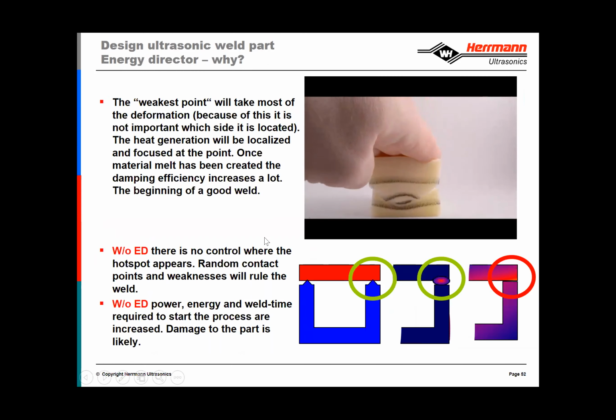And so furthermore, an energy director is absolutely required. If we had a situation like over here on the right, where the energy director is missing or lacking, the entire surface of the part typically is where the heat affected zone goes to, and that's undesirable. We want to focus the heat, like shown in the middle graphic here, that the heat affected zone is only within where the weld is supposed to happen, not heating the rest of the part or further away from the joint.